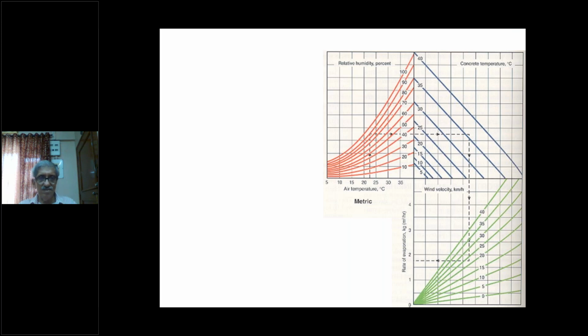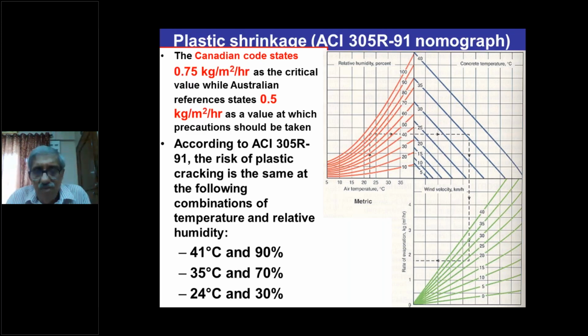Plastic shrinkage, as per the ACI 305R-91 nomograph, which most of us use in hot weather concreting. The critical value as per the Canadian code is 0.75 kg per square meter per hour, meaning the evaporation taking place at the rate of 0.75 kg per square meter per hour is safe. As per Australian, 0.5 kg per square meter per hour is the safe value. You will not get plastic shrinkage cracks. Otherwise, you will get plastic shrinkage cracks if the value exceeds, depending on which code you are following.